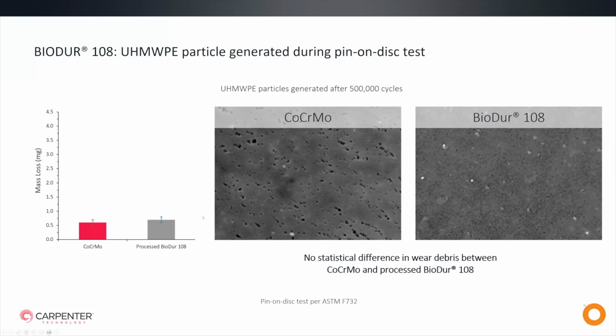After we completed the pin-on-disc wear test, we looked at surface contamination of the wear debris and also the overall pin mass loss. And as you can see in the mass loss diagram, which is just a truncated version of what I showed you a moment ago, and also in the images here, there's really no statistical difference between the two from a pin loss after 500,000 cycles.